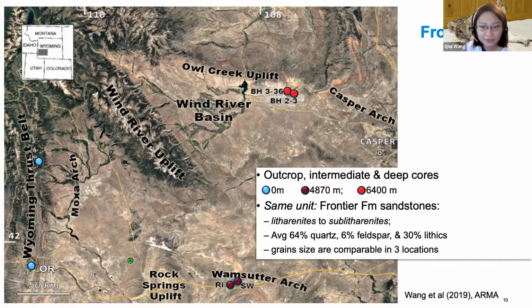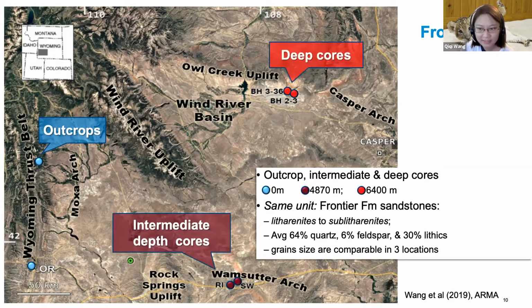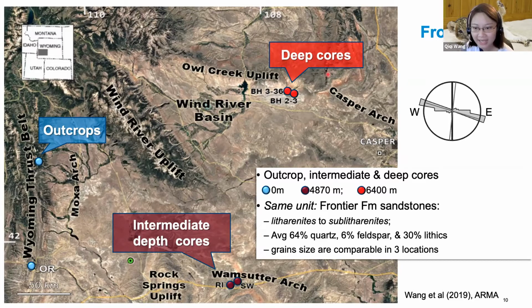Here is a map showing the studied Cretaceous Frontier Formation sandstone outcrop and well locations. Lithology is consistent throughout the study area. The samples have the same composition, litharenites to sublitharenites, and the grain size is comparable among the 3 locations. I picked the same fracture set across the basin. Now, the only difference between the outcrop, the intermediate, and the deep core scenario is that they are at different present-day depths. That is to say, we sampled over a wide range of thermal histories to investigate quartz cementation within natural fractures.